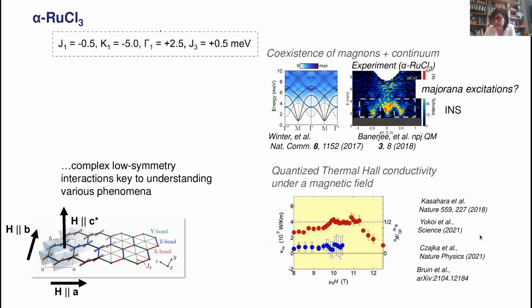This is, in principle, what the group of Yuji Matsuda in Tokyo measured for this alpha-ruthenium trichloride. However, these are very controversial measurements, and there is a lot of discussion about whether this quantization has been observed or not, which would tell us that after suppressing the long-range magnetic order with a magnetic field, there would be an intermediate phase of chiral spin liquid.